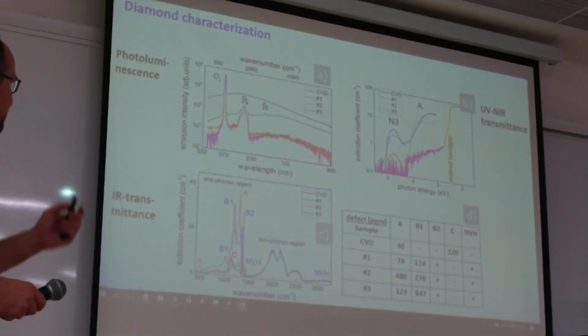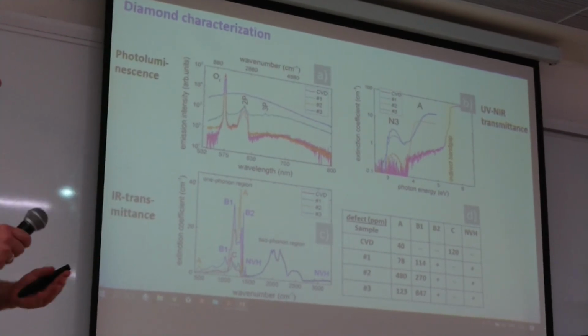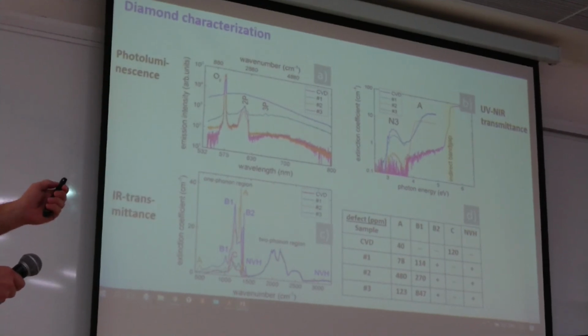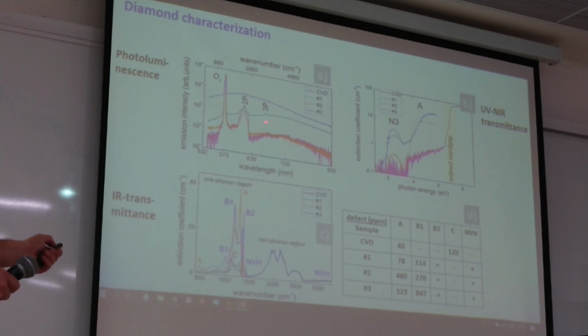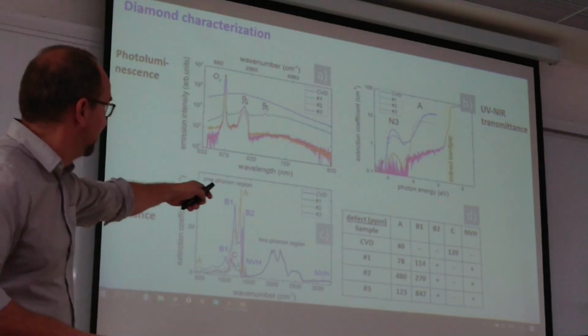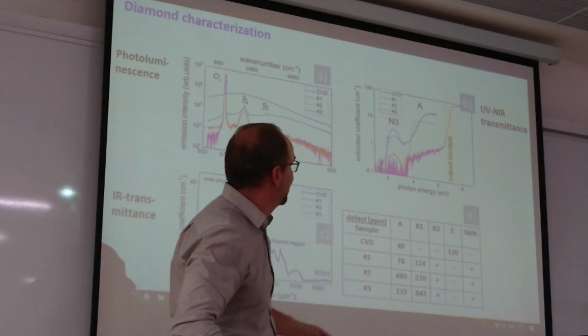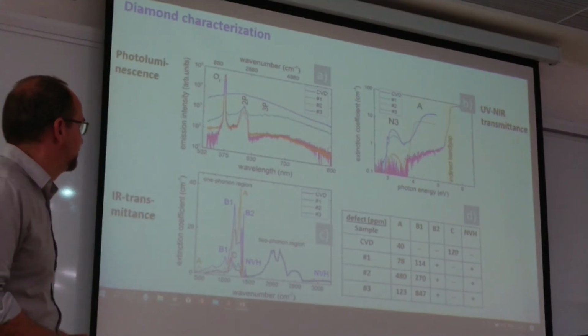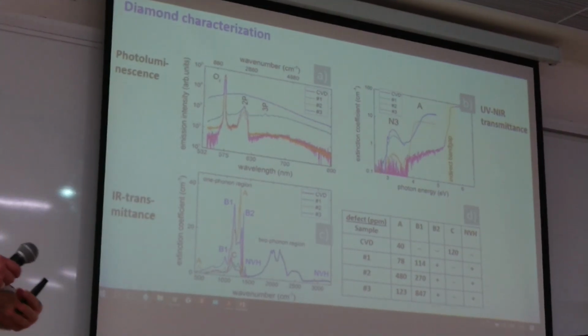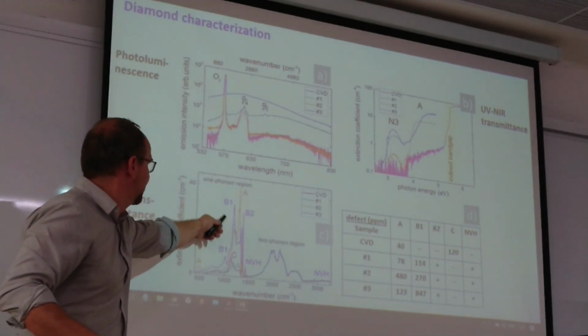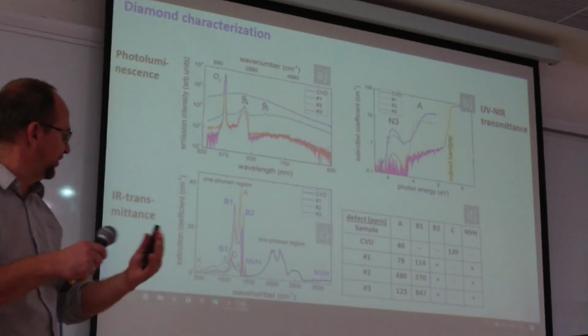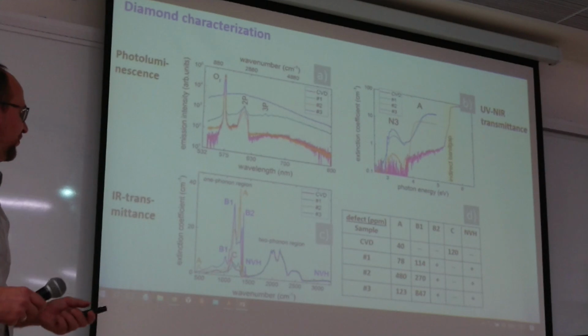Okay, but let's switch to the further. Diamonds, as I told, have many different color centers, and so the optical properties of diamonds are very different. Here you can see photoluminescence. There are four types of diamonds, and luminescence spectra are very different. This is a logarithmic scale, so you can see some centers are low luminous and some high luminous. In UV, near-infrared spectroscopy, you can see that some centers are strongly present in transmission, and some are not. Infrared spectroscopy shows the abundance of different centers, and this table shows that their content abundance can be very, very strong.